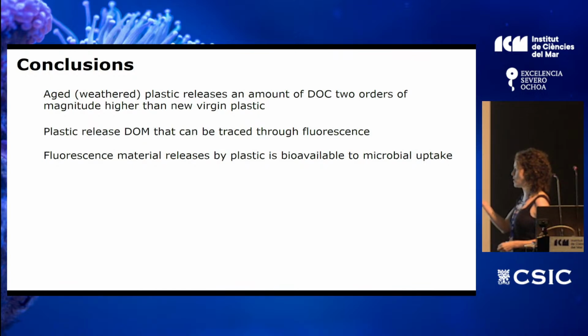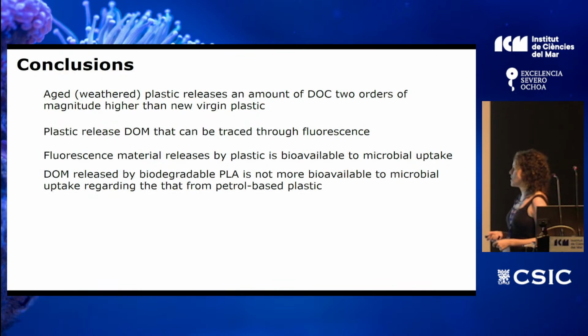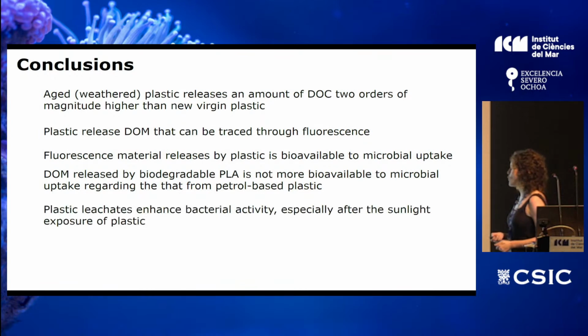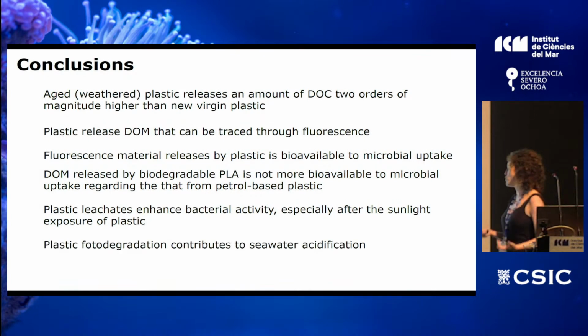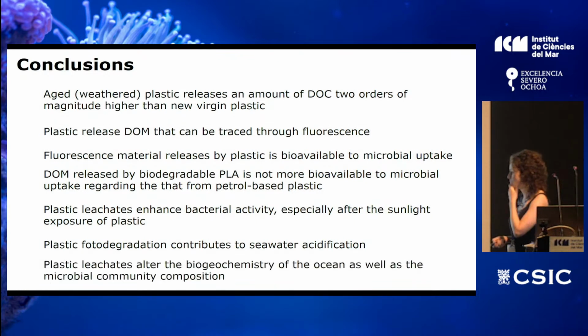Then we also saw that the fluorescent material released by plastic is bioavailable to microbial uptake, and that the DOM released by biodegradable plastic is not more bioavailable to microbial uptake than that from petro-based plastic. We also found that plastic leachate enhanced bacterial activity, especially after sunlight exposure of the plastic. And plastic photodegradation contributes to seawater acidification. And to end, plastic leachate alters the biogeochemistry of the ocean, at least of the surface in very polluted areas, as well as the microbial community composition.